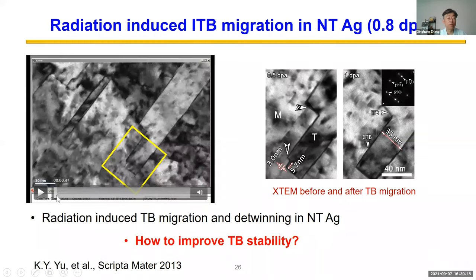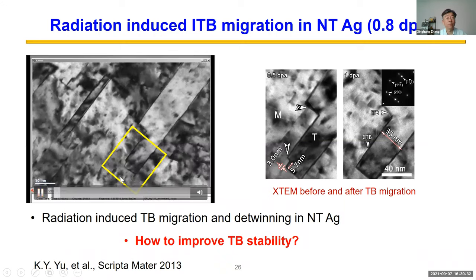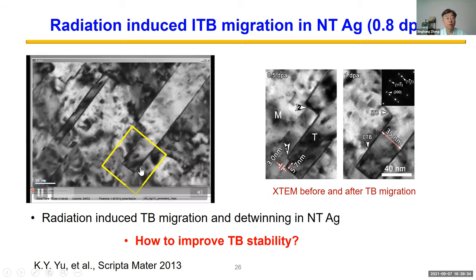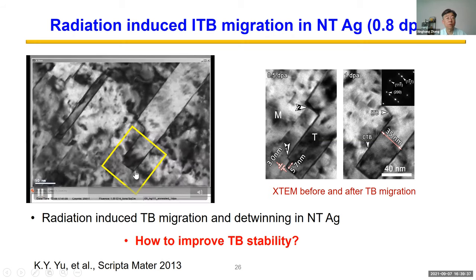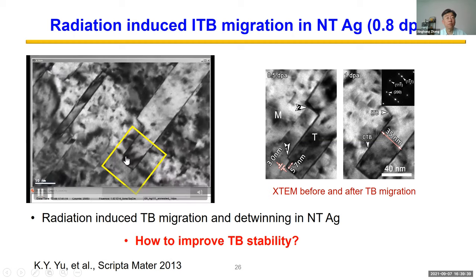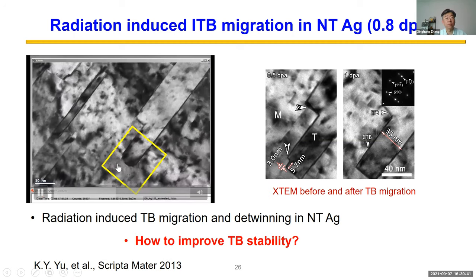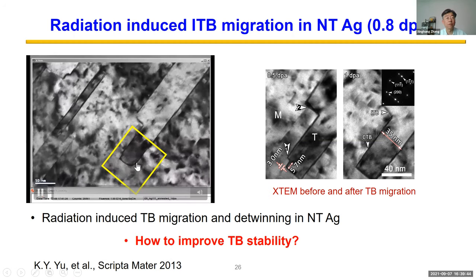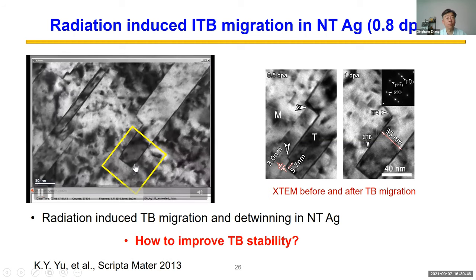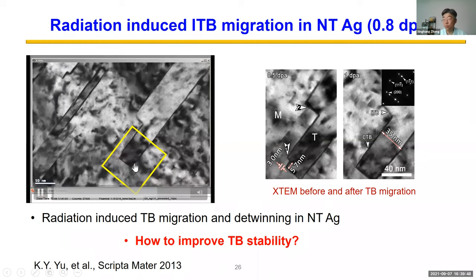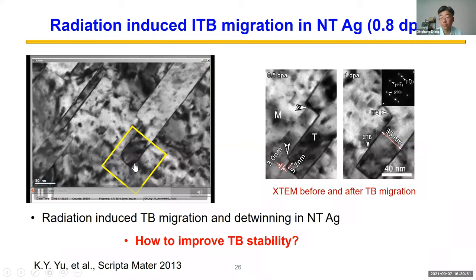So if I start from the beginning, notice there's a very tiny step right here. And this is the dimension of that step, and after radiation, again, the krypton ion beams, this step disappeared. So we play that video. So notice this sharp corner and this orthogonal corner. And there's pretty rapid interaction in detwinning process. And this corner now become blended. So there's a lot of detwinning events going on, and the twin boundary keep evolving during radiation.